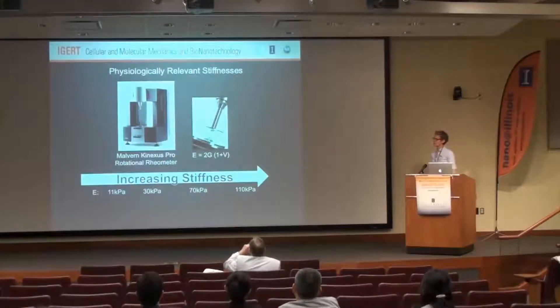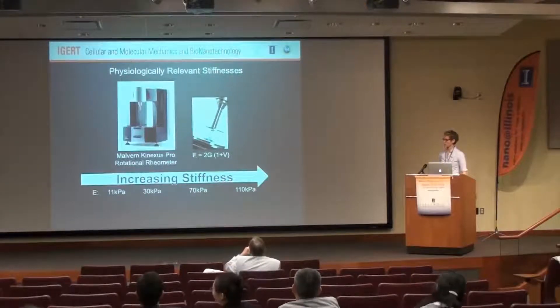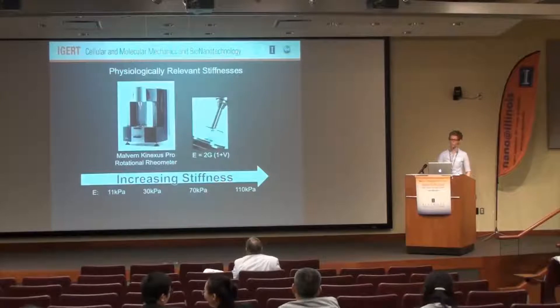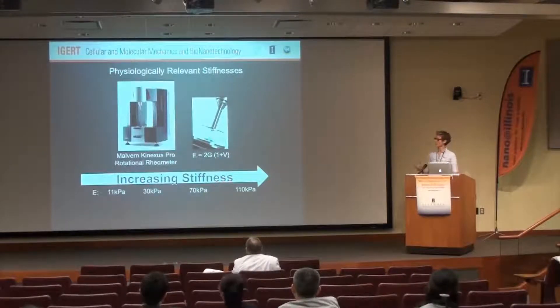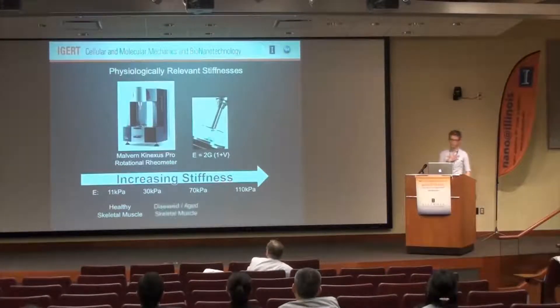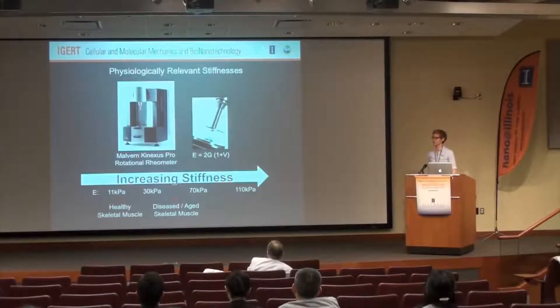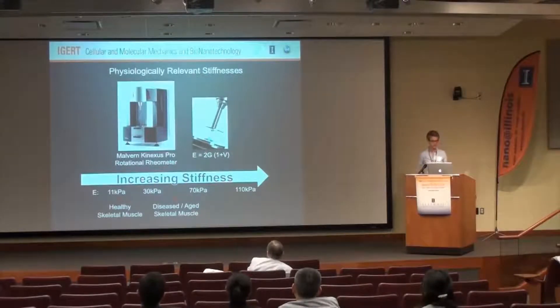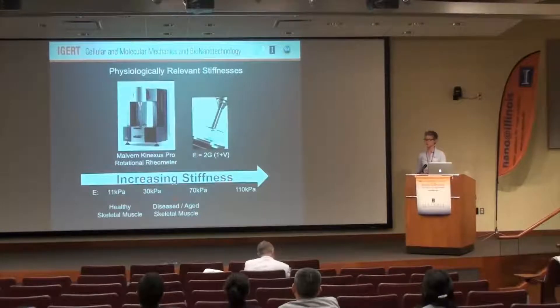What we were able to come up with is a range of stiffnesses from 11 kilopascals all the way to 110, tested by determining the shear modulus with a rotational rheometer. Significant for my work is that within that range you have the physiologically relevant stiffnesses of both healthy skeletal muscle and diseased, aged skeletal muscle, because as you have disease progression you have increasing stiffness.